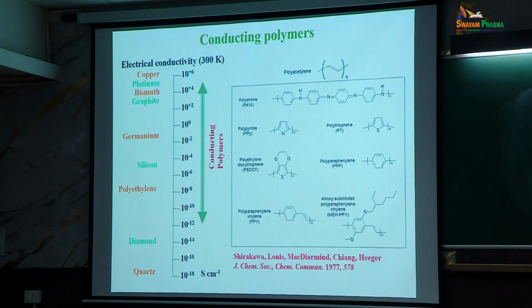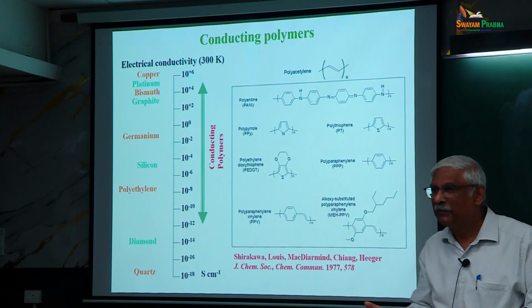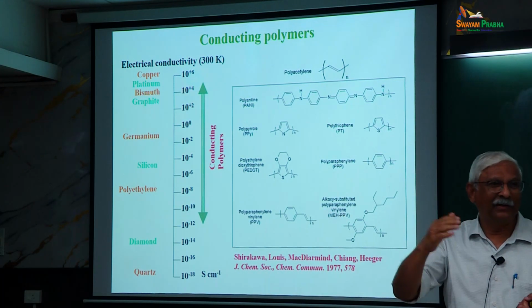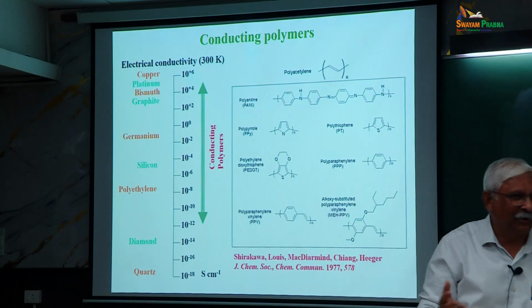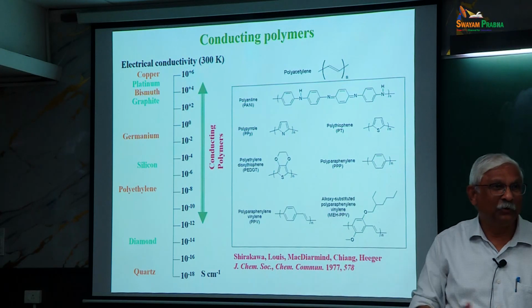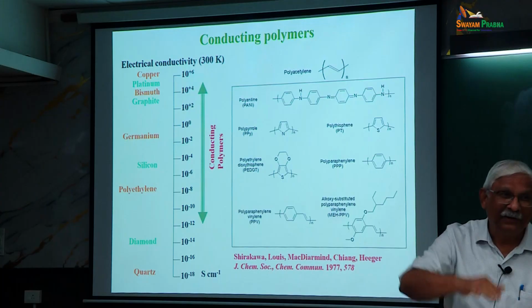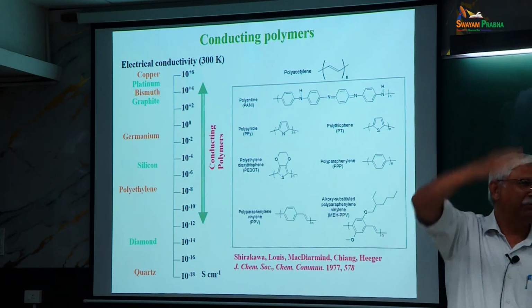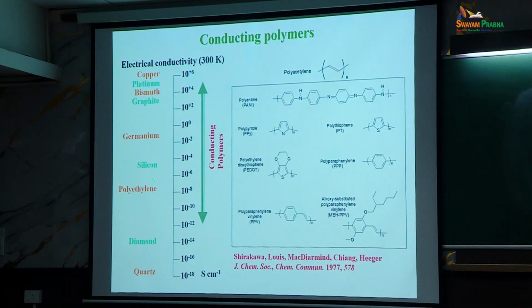You see, melting point of compounds. How much variation will you have? 50 degrees, 70 degrees, 100 degrees, 200 degrees, 300 degrees, that's all. But electrical conductivity goes from 10 power minus 18 to 10 power plus 6. Huge variation. Now, what is interesting about these conducting polymers, you can make them with a variety of conductivities by changing the structure, by changing what is called the doping and so on. So that is the beauty of these materials. They are polymers, but electrically conducting, and you can play with their conductivity.